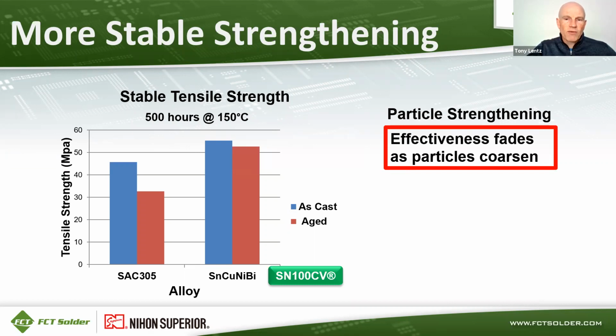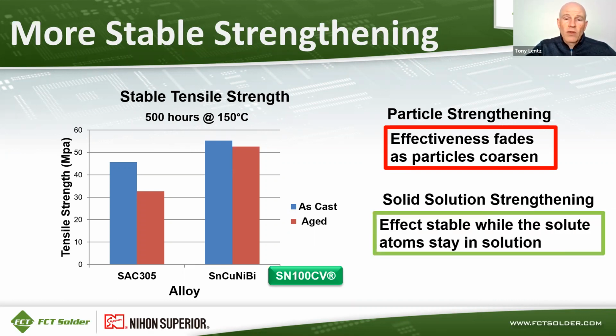And that's the difference between particle strengthening, which is what SAC 305 uses, where the effectiveness fades as the particles coarsen through aging. Whereas solid solution strengthening, which is what's used in SN100CV, is very stable because the bismuth stays dissolved into the tin matrix.